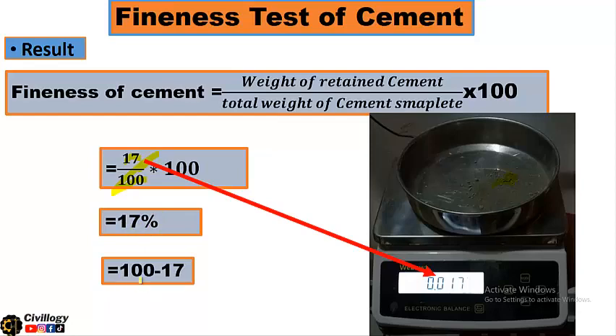Now if we subtract 17 from 100, we get 83%. This shows the fineness of cement is 83%, meaning the particles which made their way through the sieve are 83%. 83% of particles are fine and 17% are residue. So this type of cement will not be recommended and should not be used for high importance buildings and structures.